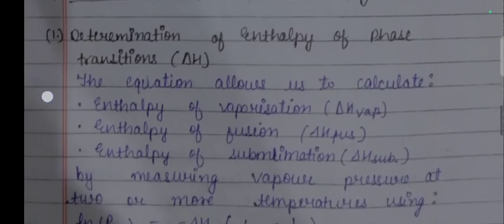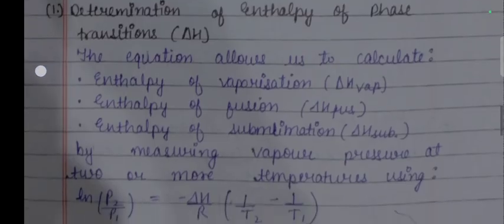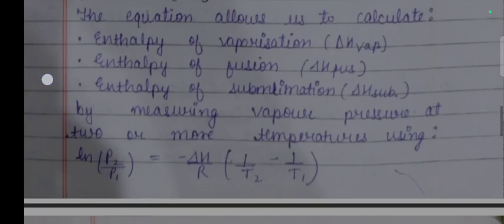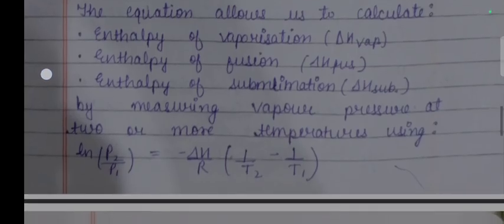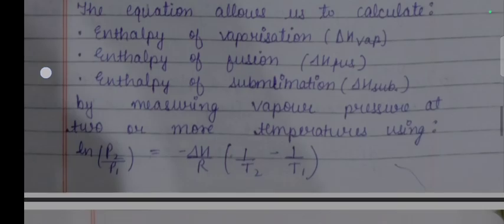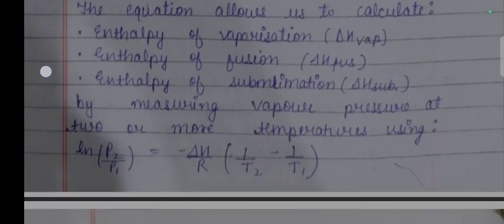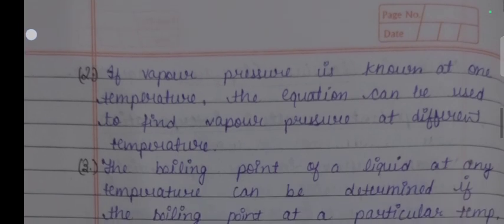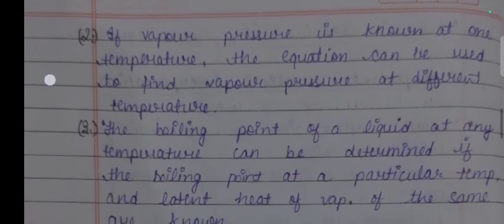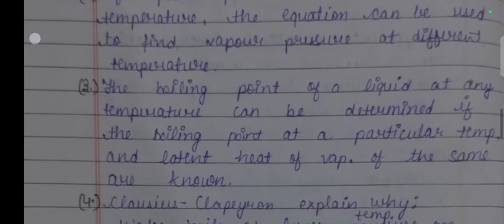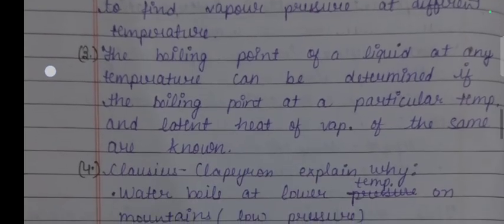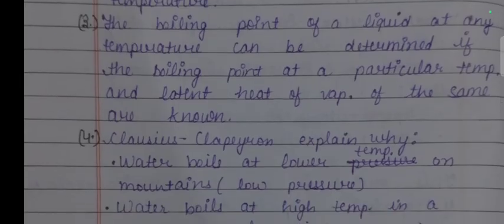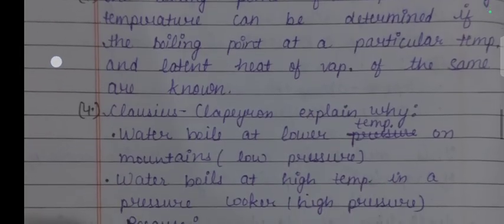Applications of Clapeyron equation. First, determination of enthalpy of phase transition delta H. The equation allows us to calculate enthalpy of vaporization, enthalpy of fusion, enthalpy of sublimation by measuring vapor pressures at 2 or more temperatures using ln P2 upon P1 is equal to minus delta H upon R into 1 upon T2 minus 1 upon T1. Second, if vapor pressure is known at one temperature, the equation can be used to find vapor pressure at different temperature. Third, the boiling point of liquid at any temperature can be determined if the boiling point at a particular temperature and latent heat of vaporization of the same are known.